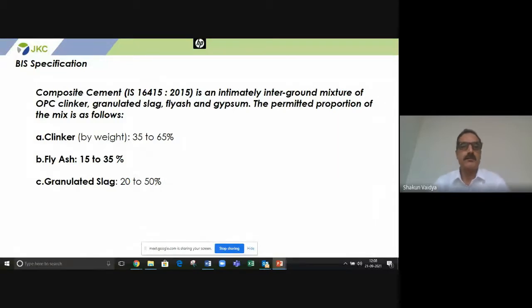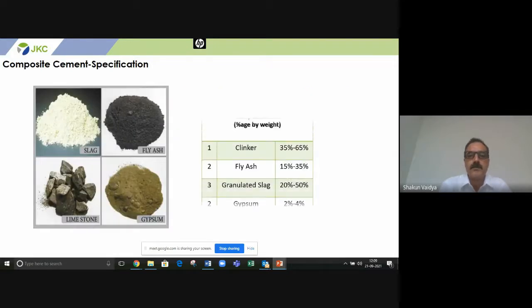So composite cement, if we go by definition, is an intimately ground mixture of OPC clinker, granulated slag, fly ash and gypsum. The permitted proportions as per IS 16415 are that the clinker proportion varies from 35 to 65%, cannot be less than 35, can go up to 65. Fly ash proportion is 15 to 35%, GGBS is 20 to 50%, but the combined blending of fly ash and slag cannot exceed 65%, on the lower side 35%. So this is the broad guideline given by the Bureau of Indian Standards. Again, the same specification has been given here.